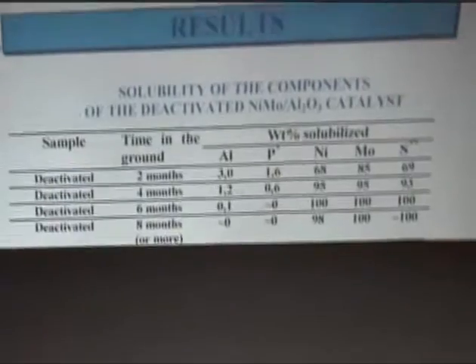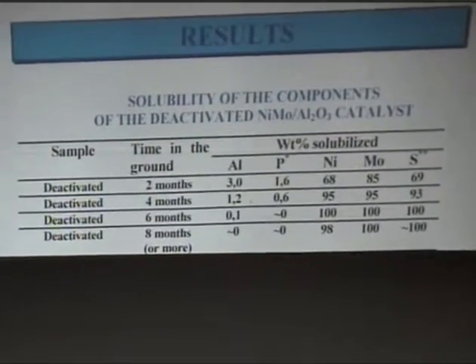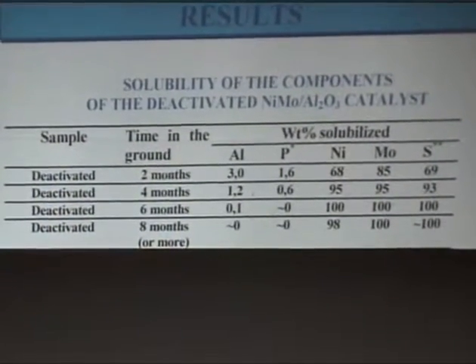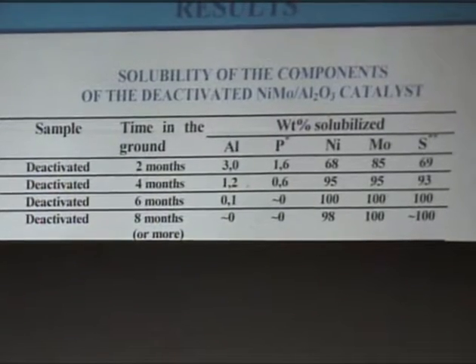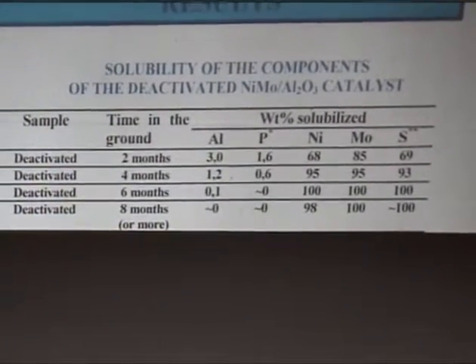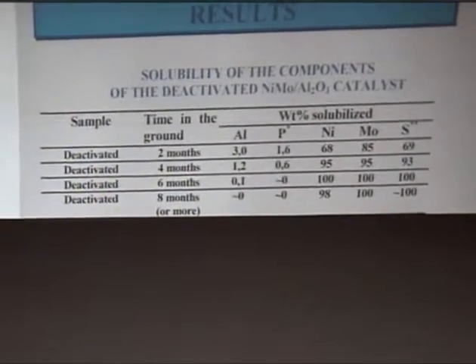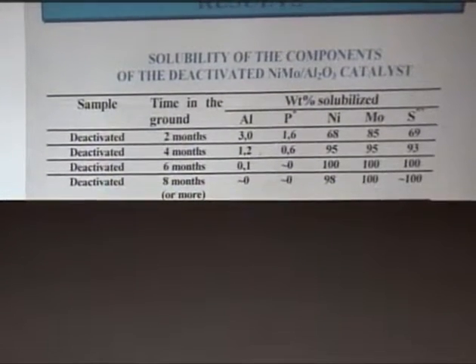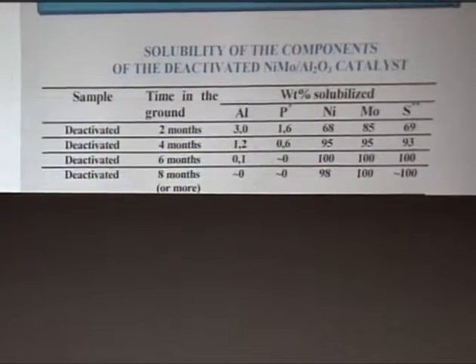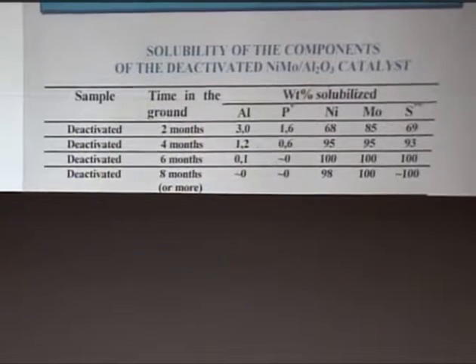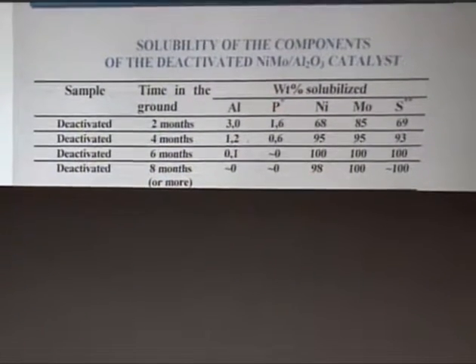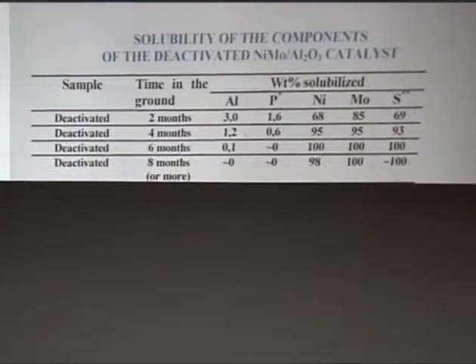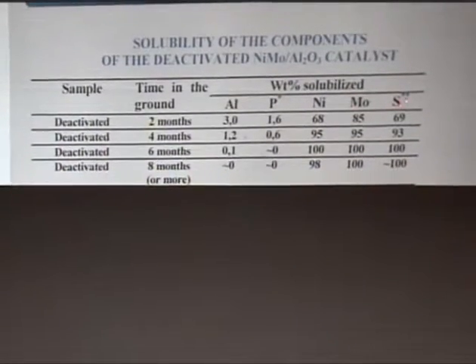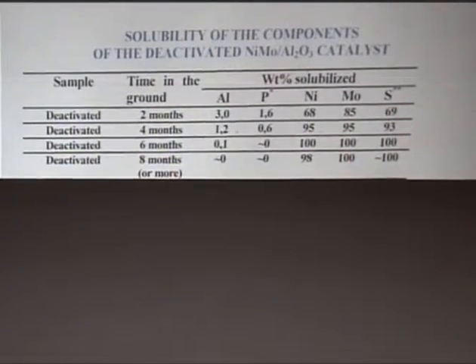Now, we are going to discuss the results, and first of all, we will get some insight into the overall solubility of the components of the deactivated NiMo catalyst. The results presented here are from the deactivated catalyst that was not fully oxidized. As you can see, as time goes by, aluminum and phosphorus become fully insoluble, whereas nickel, molybdenum, and sulfur show quantitative solubilization levels.